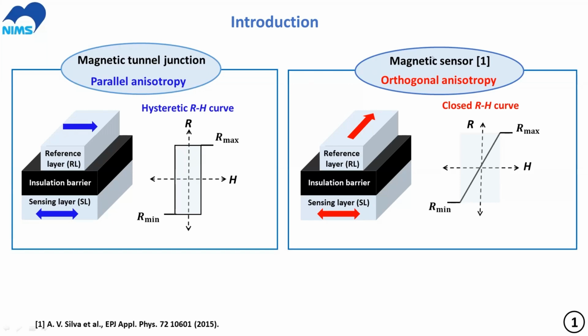On the other hand, in order to use a magnetic tunnel junction as a magnetic sensor, the transformation between R maximum and R minimum and vice versa should go linearly like this, and we call this coherent rotation of the magnetization of the sensing layer with the reference layer. And you will only get this very linear transfer curve, or hysteresis-free curve, if the magnetization direction of the reference layer is orthogonal to the sensing layer.